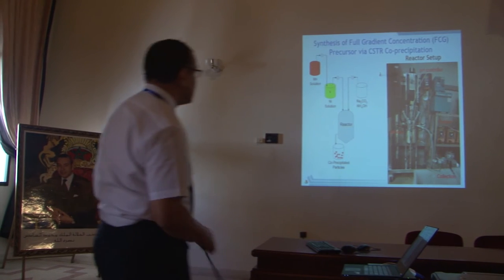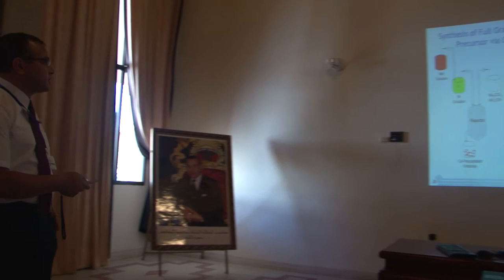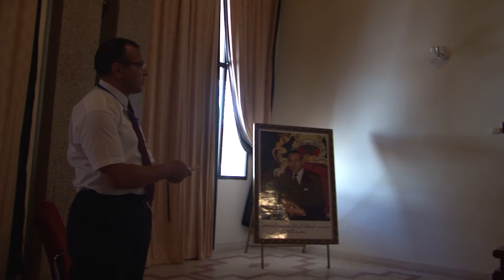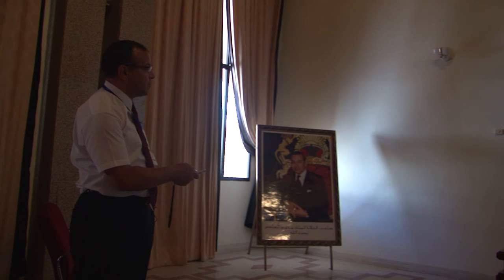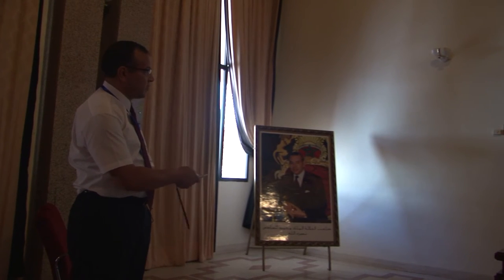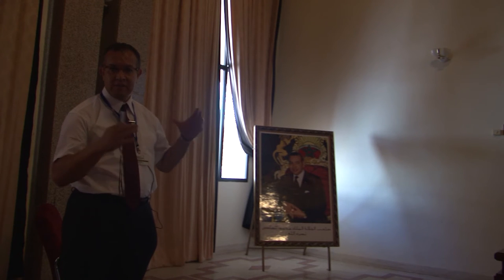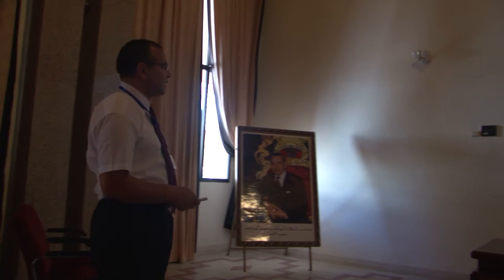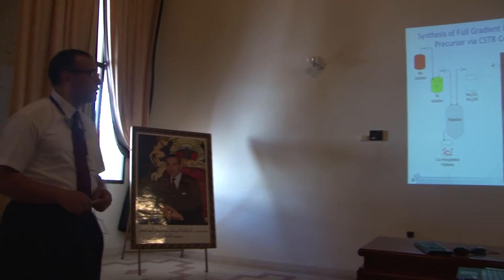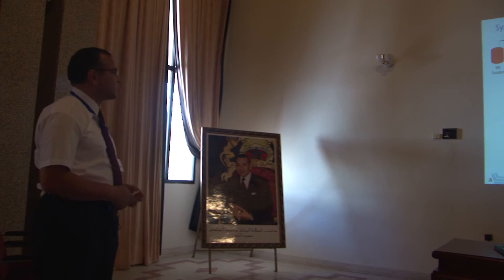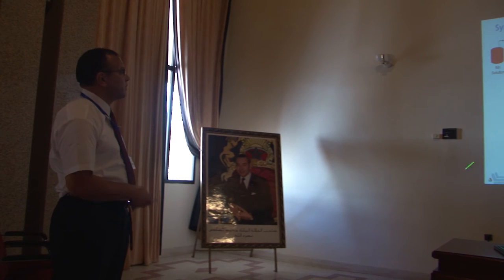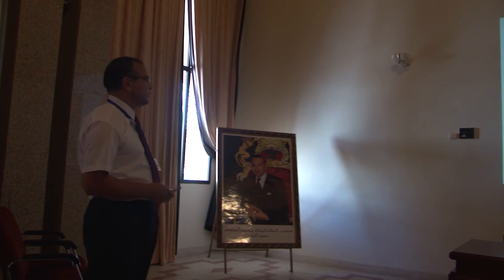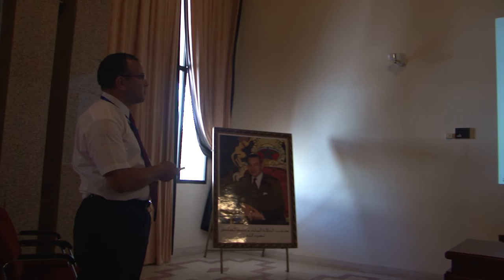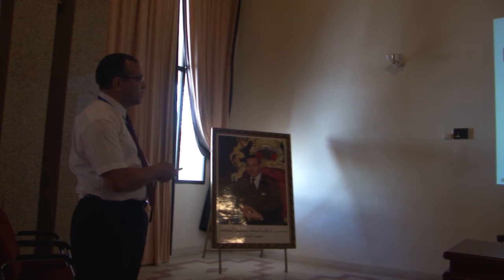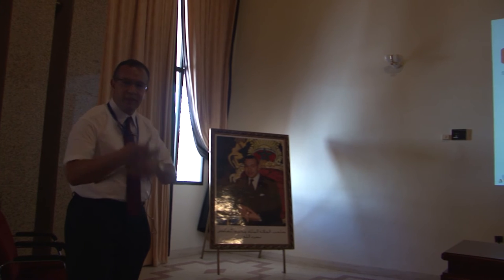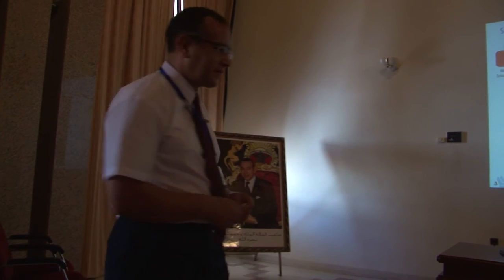And the way of doing it is very simple. This is the co-precipitation. Most of the companies that make nickel NMC, for example, use this process up to now. So you have a nickel cobalt manganese concentration that is stable. You put it in the reactor, you add a chelating agent and a co-precipitation agent like sodium hydroxide, for example. And then you form a spherical material. What you do in this case, you add another tank that is manganese-rich. You start with nickel-rich and immediately start diluting the nickel with the manganese, so you end up changing the composition as the particle is growing.